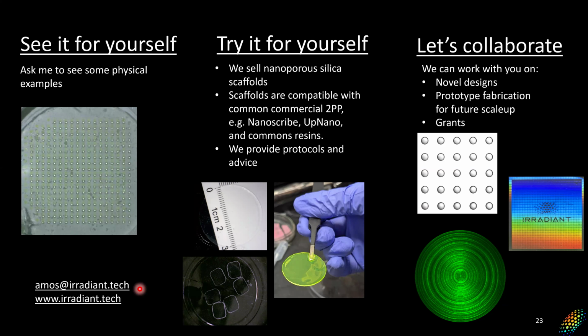Can you recommend a material that would match the CTE of your components? Yeah, the CTE for them is pretty similar to silicon. I always forget if that's higher or lower than silica, but it's usually closer to silicon than silica, somewhere in between typically.